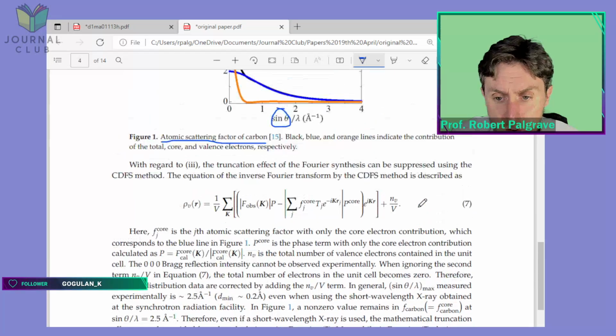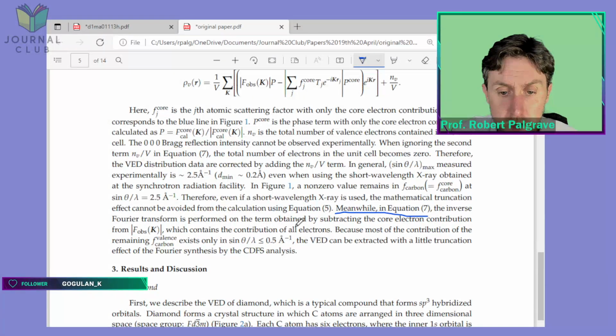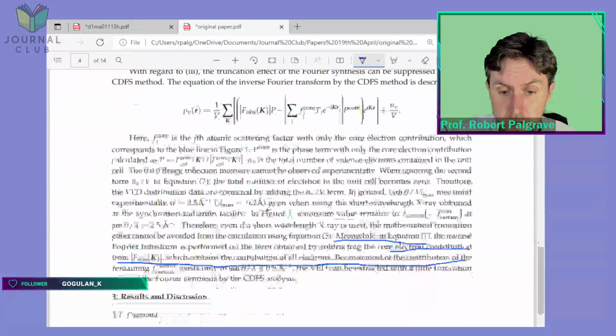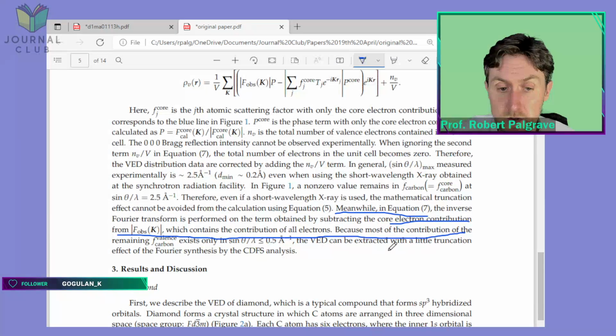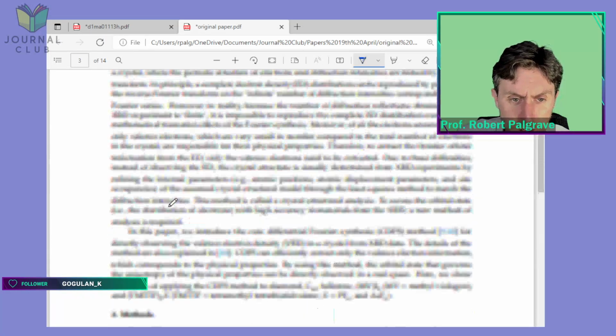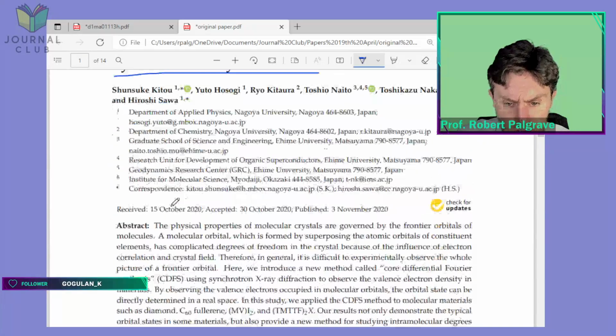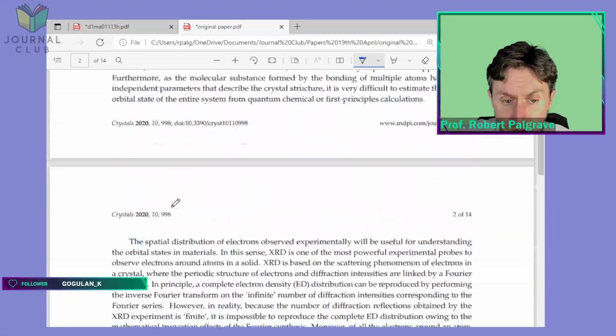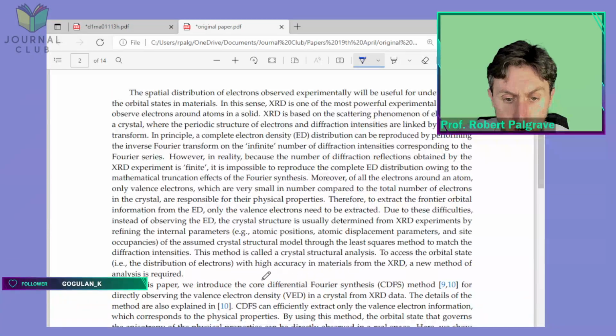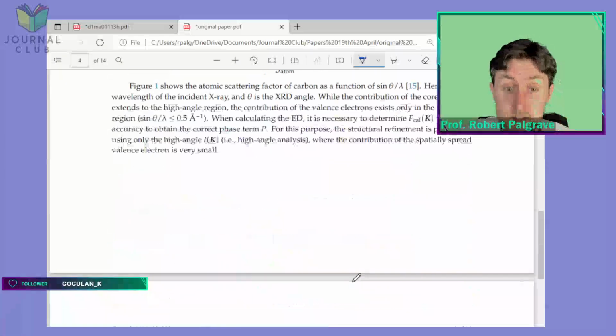Meanwhile, in equation 7, which is this equation up here, the inverse Fourier transform is performed on the term obtained by subtracting the core electron contribution from the observed structure factor, which contains the contribution of all electrons, because most of the contribution of the remaining valence scattering, the scattering factor of the valence electrons, exists only in this very low angle region down here where we said before. The valence electron density can be extracted with little truncation effect of the Fourier synthesis by the CDFS. That's the name of this technique, which I've forgotten. What does CDFS stand for? There you go. Core differential Fourier synthesis. Okay, so that's how they overcome this truncation problem.